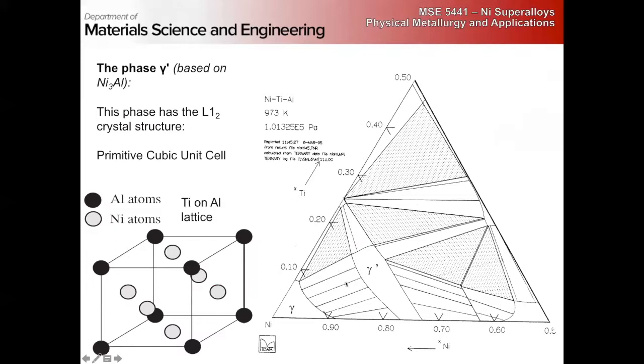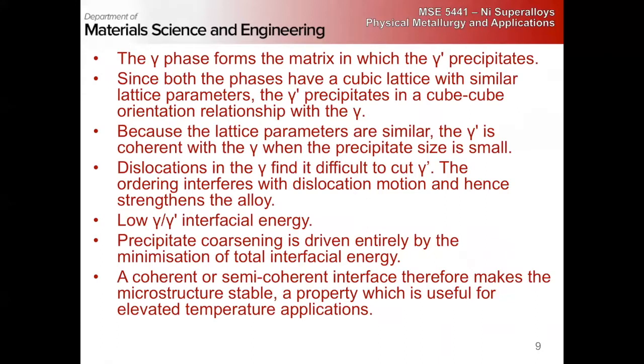All right? Okay. So our gamma phase forms the matrix. Gamma prime is the precipitate. Both phases have a cubic lattice, with very similar lattice parameters. So we have a cube-cube orientation relationship with the gamma, right? So we have a coherent interface where the a, b, and c crystallographic axes in the gamma and the gamma prime are all parallel with each other, right? So we have a coherent matrix.